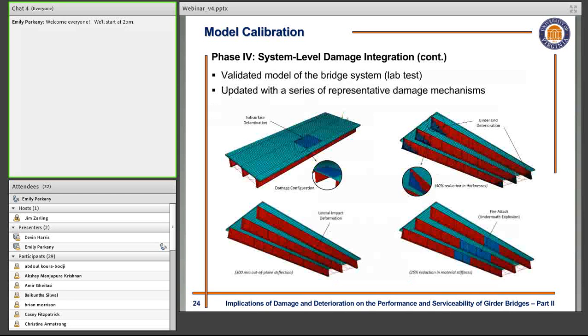In this phase, we started our investigation with a little sensitivity analysis, and we updated one of the bridge models that we validated in phase 2. This was the bridge that was tested at the University of Nebraska. That was a lab test bridge, and we tried to include some representative cases of damage in the model, like delamination, corrosion in the girders, lateral deformation as a result of vehicular impact, and also fire attack. We didn't have any exact idea of the values of the damage or the location at the time, so the damages that we put on this structure are ideal representations of the actual quantities that may be found in practice.